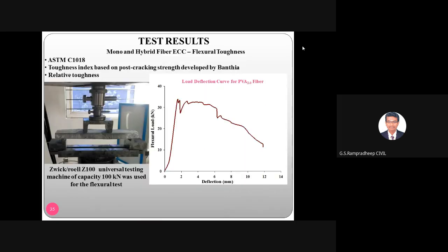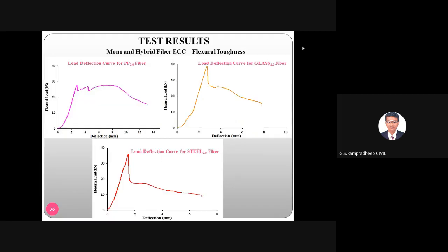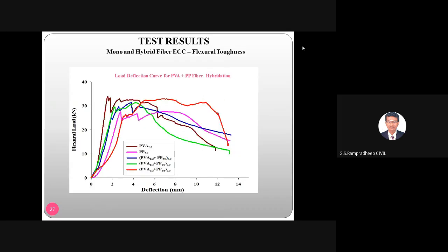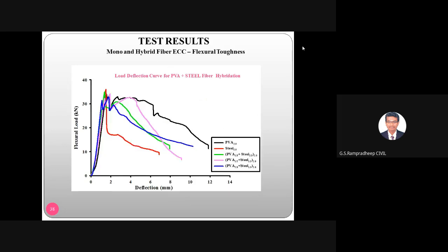But carefully observe the deflection. If you are adding PVA low modulus fiber, the deflection is more, and obviously the flexural peak load is also less compared to the glass, where your ultimate deflection is coming around 7.9 and the maximum flexural load carrying capacity is coming around 39 kilonewton. Just compare with the high modulus fibers, glass and steel. Leaving aside the low modulus PP, you get very little deflection with the maximum load carrying capacity. And this is the combination of all the fibers, where you can get the maximum load with respect to the deflection hybridization.